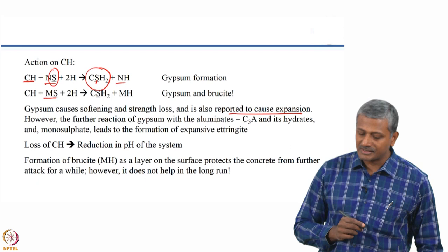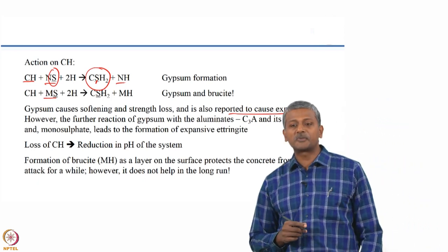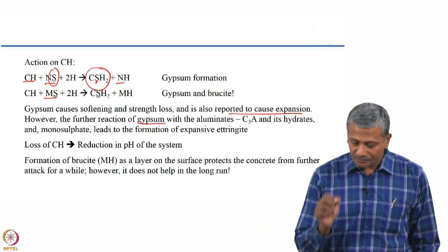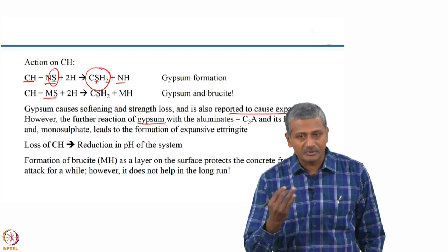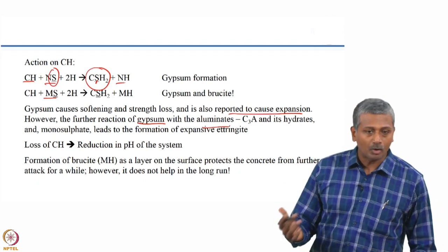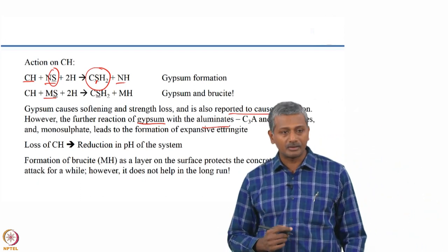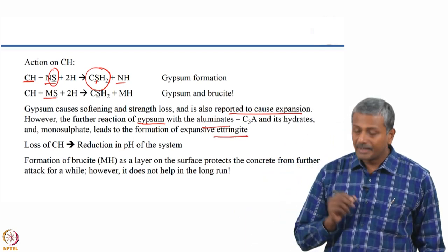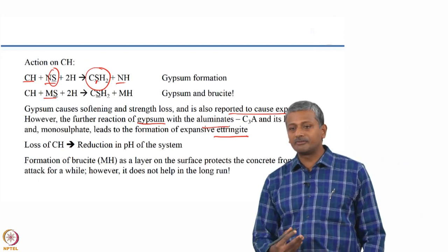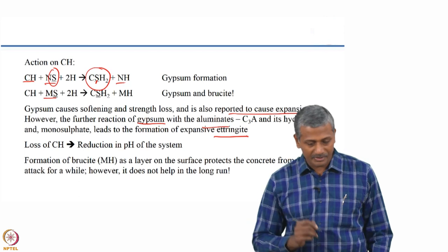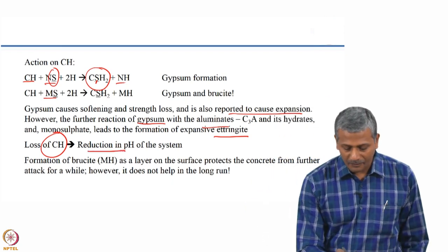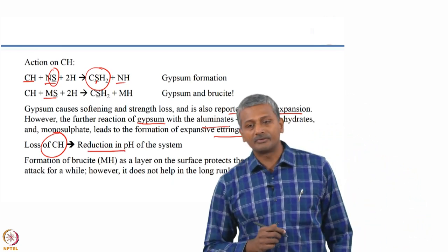Just as happens in fresh cement paste, this gypsum can react with aluminates — involving C3A or hydrated forms like monosulphate or calcium aluminate hydrate — to reform expansive ettringite. That is probably the most deleterious stage of this reaction as observed in laboratory experiments, though in the field something different happens. One major issue is that you are losing calcium hydroxide, causing a reduction in the alkalinity of the system. In the case of sodium sulphate attack, sodium hydroxide is also produced, so the alkalinity loss is not that great and the surrounding environment remains fairly alkaline.